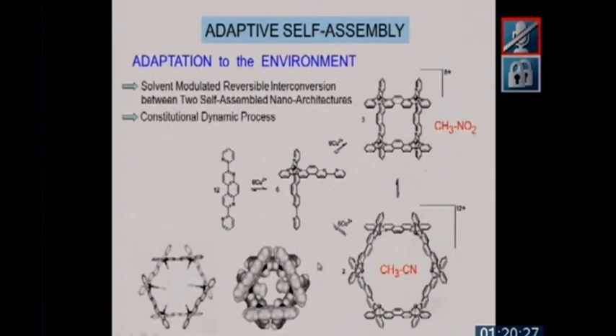Another example of this adaptive self-assembly is that when you take now this ligand, treat it with copper-2, when you operate in nitromethane, you get a square. When you operate in acetonitrile, you get a hexagon. What is the reason for that? Nitromethane is a bad coordinating solvent. It does not coordinate well. Copper-2 would like to be pentacoordinate. I already mentioned that earlier. But in nitromethane, it's a bad solvent, so it cannot coordinate. And so it just does what it can by itself, and it forms this unhappy grid 2 by 2. But that's what is the best in this solvent.